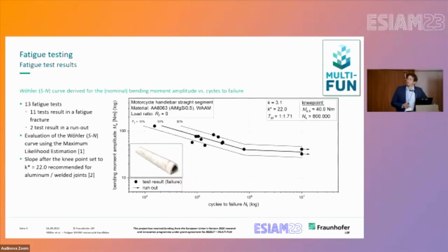Straightforward, the fatigue test results in an SN curve, so more or less in a bending SN curve, giving a comparatively high scatter of 1 to 1.7. If we compare it with welding, for example, where we usually have 1 to 1.5 as a reference, it's a little bit higher. The slope in the high cycle fatigue regime here is around 3.1, and a knee point at close to 800,000 cycles, evaluated from 13 tests, and the maximum likelihood evaluation in this case.